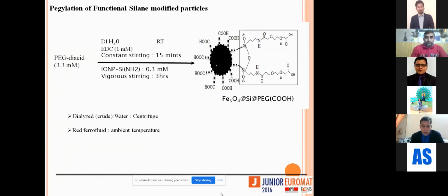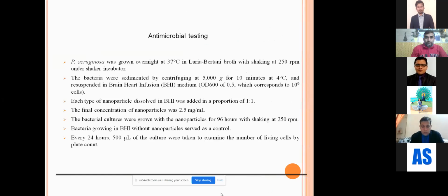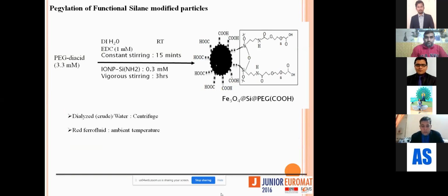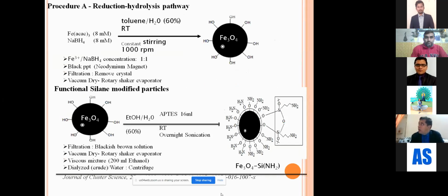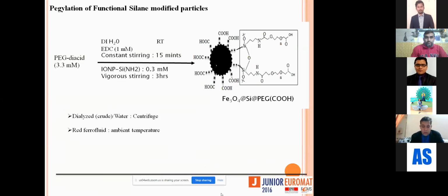So we have developed two kinds of system. One where we have incorporated silane and developed the carboxylic group onto the surface, and the other one where we have tried developing the amine group onto the surface. In the previous slide you can see the amine group was there, and the other one we have developed the carboxylic group.